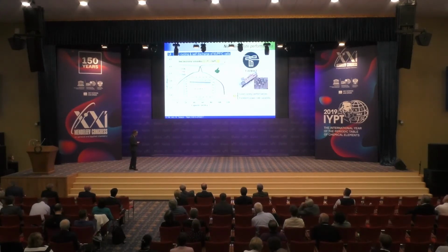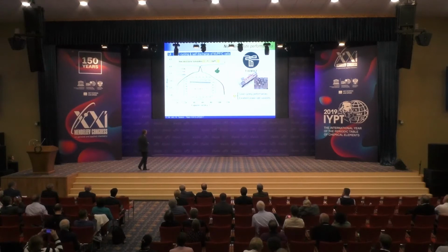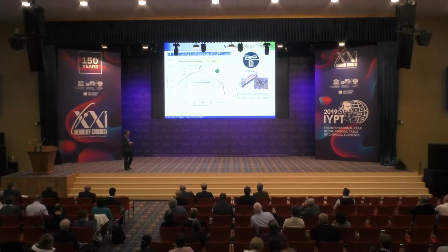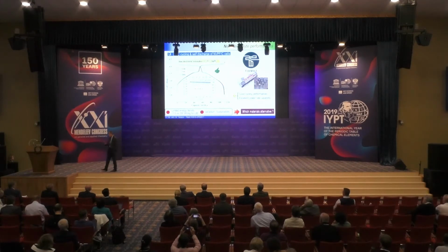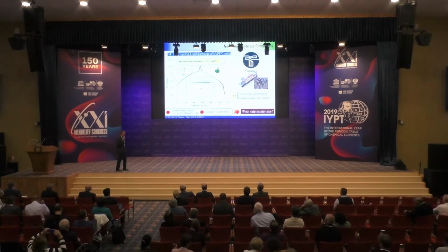And this has led to the creation of a company, Tiamat, for commercializing this kind of sodium-ion cells. But when you look at this, you have good cycling performance, excellent power rate capability, but still nothing is perfect, because we have a limited energy density. I mentioned about 110 watt-hours per kilogram compared to about 220 in the case of lithium-ion. And of course, I mentioned sustainability, we still have vanadium.